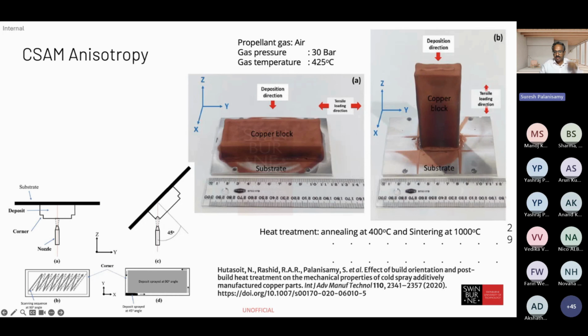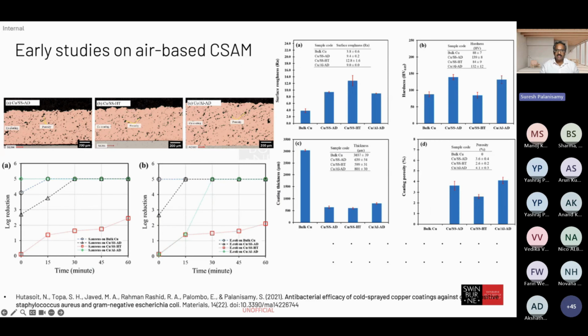In some cases this was an issue initially, so we had to machine off the excess material. We build excess parts so we only take the middle section where the properties are far better, because otherwise some sort of crack formation happens in this particular boundary section. That was visible in the early studies also, when we looked at it. Again, bulk copper was compared with copper in heat treated condition, and different heat treatment conditions were done. This is again the study on a different substrate, looking at antibacterial properties of bacteria, which can survive or which can quickly die off on certain substrates, with a stainless steel substrate and also an aluminum substrate. Both the heat treated condition and the as-built condition were studied in detail.